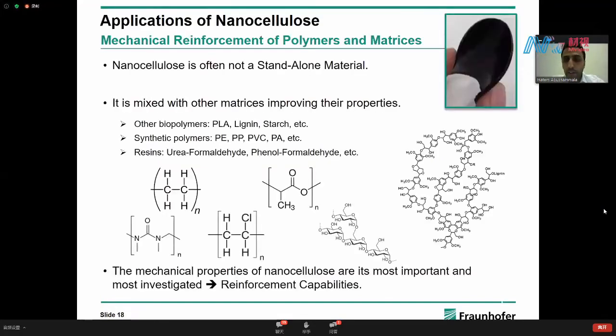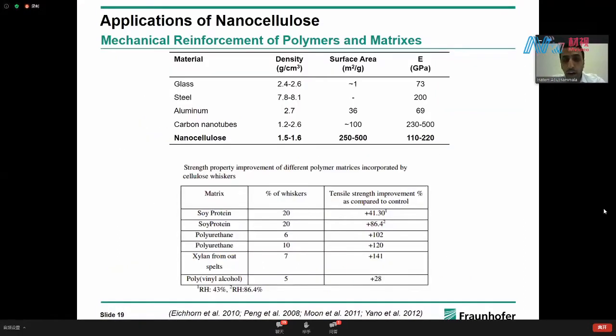The very first and the most important application, which was actually the most interesting when the nanocellulose field started, is using nanocellulose as a reinforcement material to reinforce polymers. So if you check the literature, nanocellulose has been used to reinforce biopolymers such as PLA, lignin, starch, or synthetic polymers such as polyethylene and polyamides, and also thermosets such as UF and PF resins. And this obviously has to do with the high mechanical properties and the low density of nanocellulose. And many times, the aim was also to produce lightweight composites for certain applications.